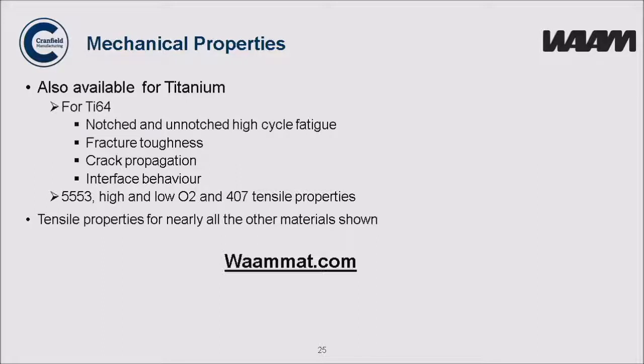I haven't got time to go through all the mechanical properties of all those materials, so you can have a look on our website, which is waammat.com. There is a lot of information about mechanical properties and systems and so on. For titanium 6-4, there's notched and unnotched high cycle fatigue, fracture toughness, crack propagation, and also the interface behavior. So you deposit it on the wrought material, you need to understand what the effect on the properties is at that interface region. And similarly for the other titanium alloys.